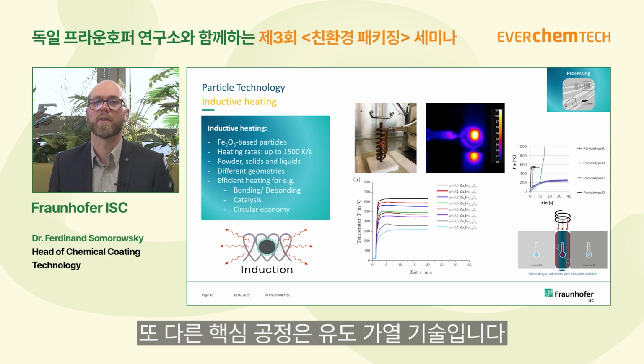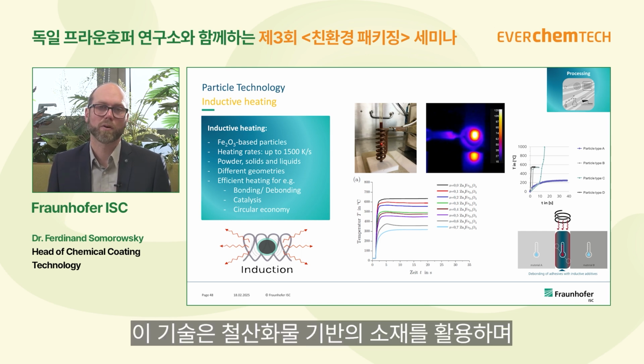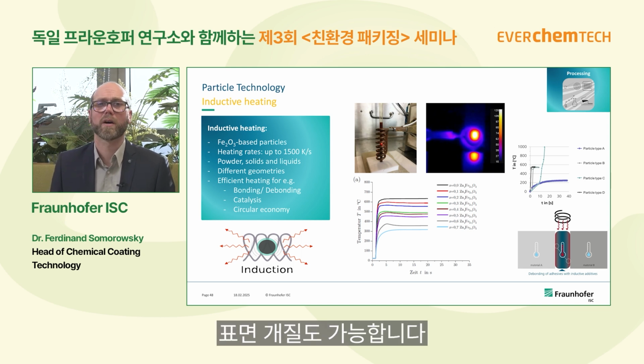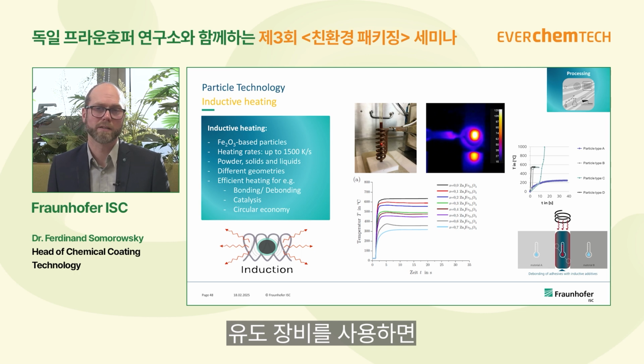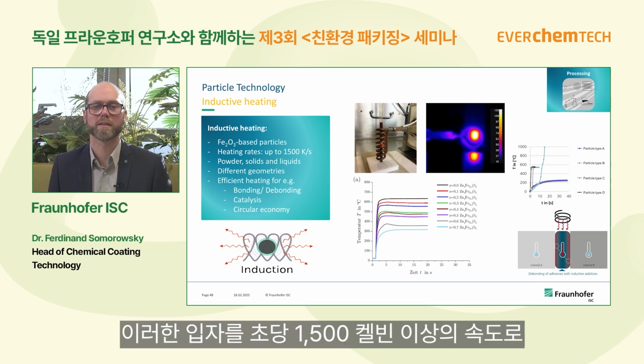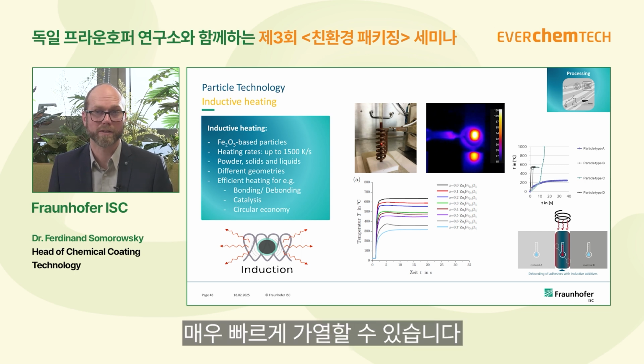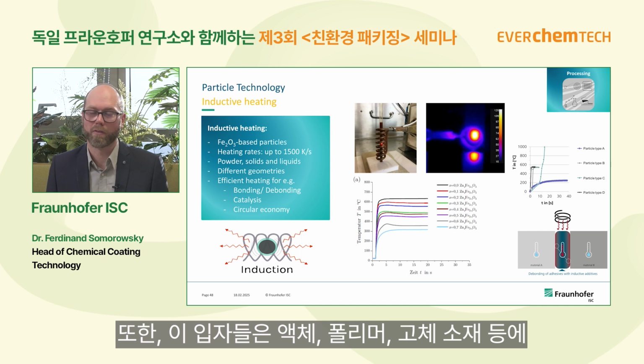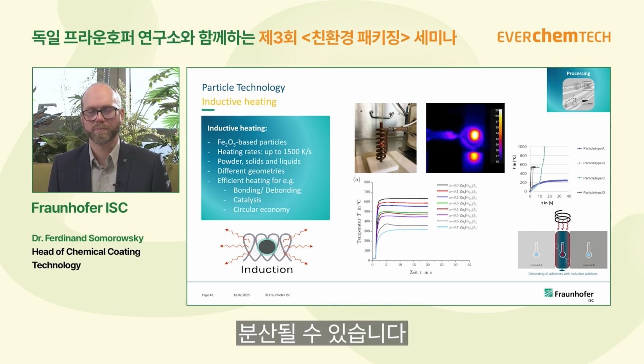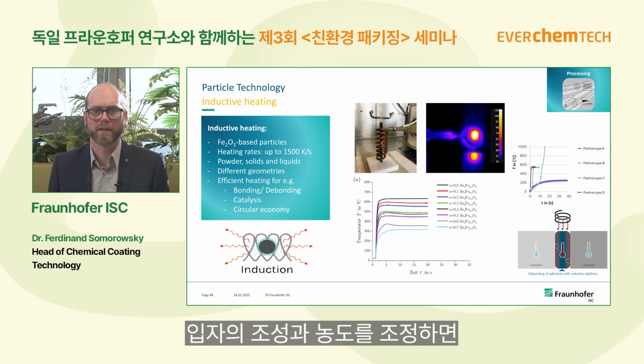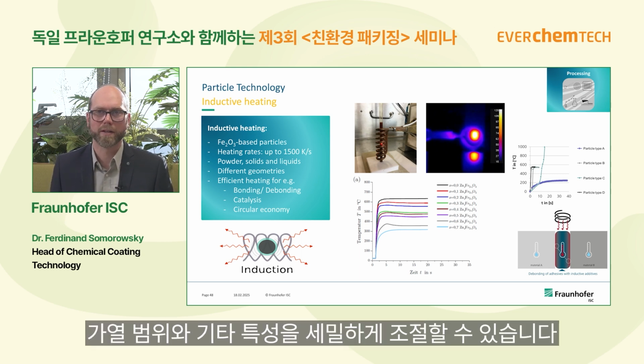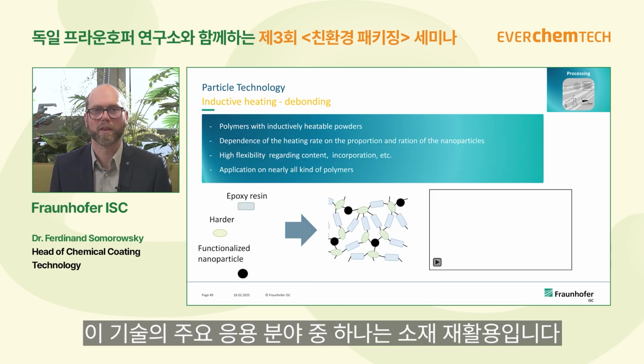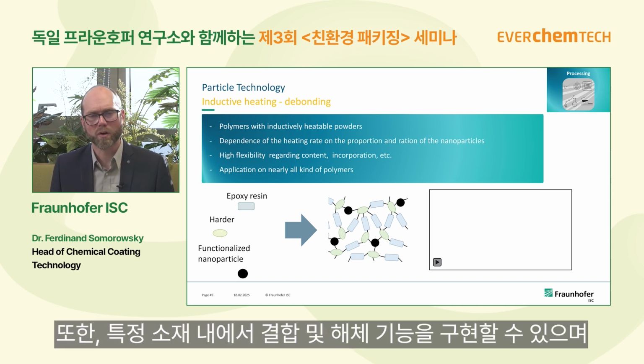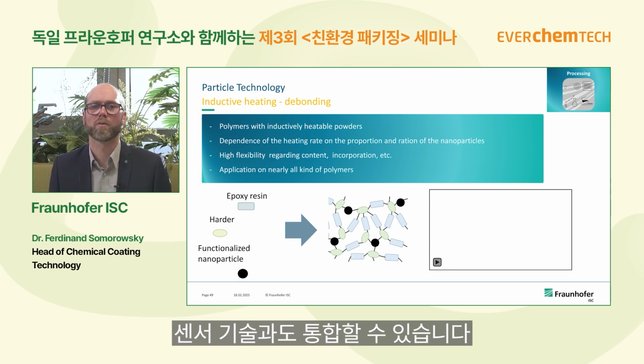One other process is inductive heating. It's an iron oxide based material which can also be surface modified, and with induction equipment you can heat up these particles very quickly, more than 1500 Kelvin per second. The particles can be dispersed in a liquid, also in polymers and solid materials, and depending on the ratio and the kind of particles, the heating range and similar properties can be adjusted very well. The idea is that it helps to recycle materials. You can also integrate bonding, debonding of the materials, and of course sensoring.